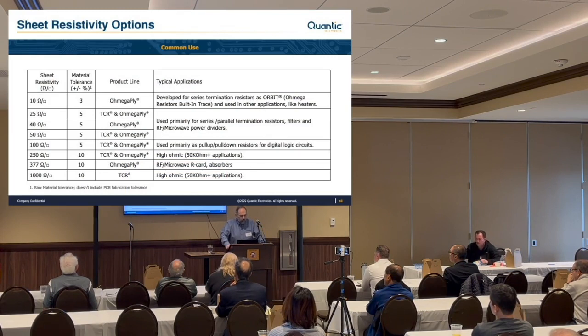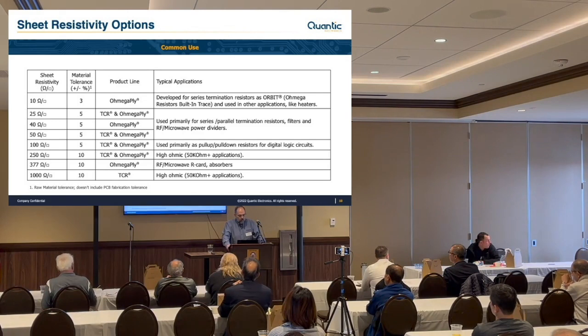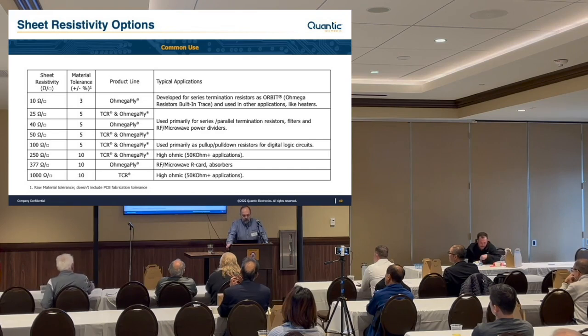So common uses, we have a range of resistive values, and I'll get into what's an interesting concept. It's ohms per square is how we define it. And so we go from anywhere from 10 ohms per square up to 1,000 ohms per square. And then I'll get a little bit into why you would pick each one. But typically the 10 ohm material is for termination resistors. You can actually put a resistor in trace, and I'll show you an example. But also people are looking at heaters now. It's a good material for embedded heater circuits.